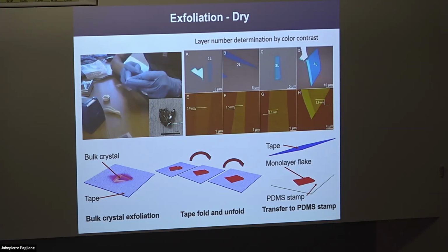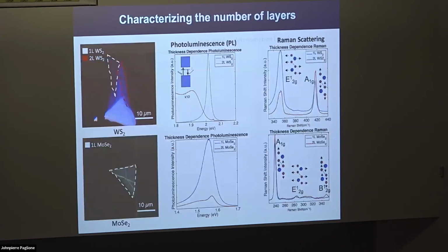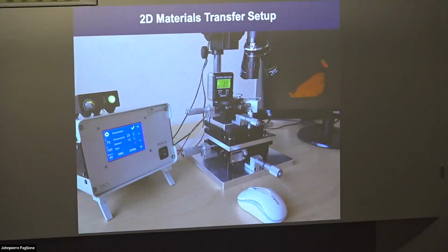You can easily measure the thickness of the layers using atomic force microscopy, right? You can also stamp these layers on something like 90 to 300 nanometers of silicon dioxide on silicon, and due to the optical contrast, you can calibrate the color, and ultimately know what number of layers you have. So you can do this very easily in any lab. That's why people like it. You can also go a little beyond and use things like Raman spectroscopy. If it's a semiconductor, you can use photoluminescence to find the layer number in these exfoliated layers. And then you can stack these layers using a variety of techniques.